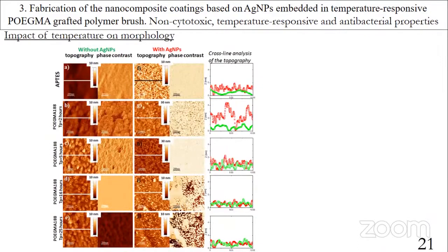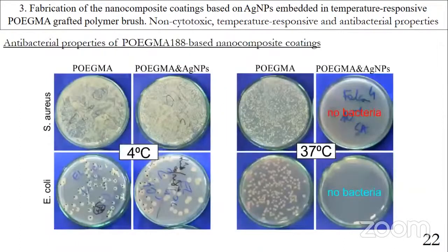To study the influence of silver nanoparticles on the morphology of the coatings, AFM analysis was performed for APTES and polymer coatings with different grafting polymerization. This slide demonstrates cultivation of two types of bacterial strains on the petri plates after incubation with the polymer-based nanocomposites and the polymer control samples at 4 degrees. At 37 degrees, almost no bacteria were visible for temperature-responsive coatings with silver nanoparticles, whereas the growth of bacteria remained unperturbed for pure coatings, indicating well-expressed temperature-dependent antibacterial properties for silver nanoparticles integrated into our brushes.